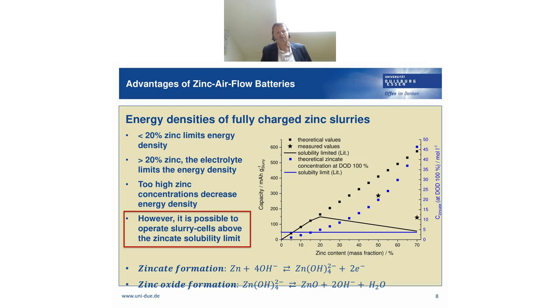So with our zinc slurries with 50 or 70 weight percent zinc, there's so much zincate produced that we cannot keep it in solution. So inevitably, our zincate will precipitate as zinc oxide. And this is really our approach, what we've done here in our group. And I will show you that it is possible to operate slurry cells well above the zincate solubility limit.